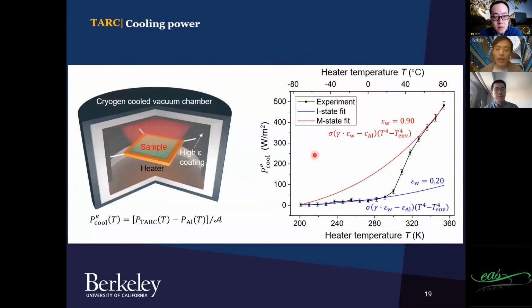And we also measured the cooling power using a cryogen-cooled vacuum chamber. We coated the interior surfaces with a high emissivity coating to simulate outer space. And we used aluminum foil for reference. So the result shows that at low temperature, the cooling power of TARC is small, and at high temperature it is really large, with a fitted emissivity of 0.9, just as the FTIR result gives us.